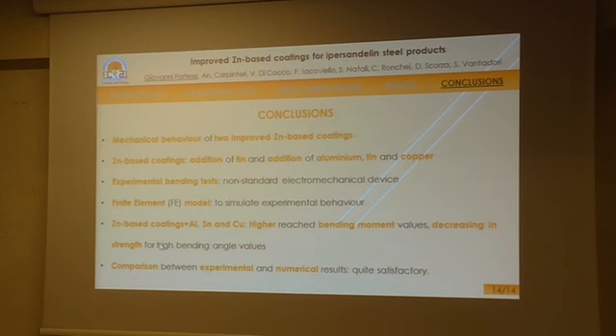For the specimens with addition of aluminium, tin, and copper, a higher activity of the melting bath has been observed, leading to higher bending moment values, but at the same time showing a slight decrease in strength by increasing half bending angle and dipping time. A comparison between experimental and numerical results in terms of bending moment against half bending angle seems to be quite satisfactory.